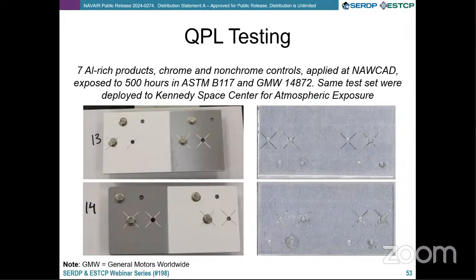We've determined that the best way to do so is using this simplified galvanic panel in two different corrosion chambers. One is your standard ASTM B117, but another is the GMW cyclic chamber, which simulates drying and wetting. We found that that's a lot more reliable at predicting coating corrosion resistance out in the environment than the B117.